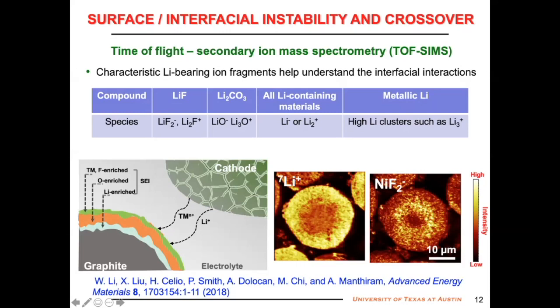We have also used time of flight secondary ion mass spectrometry. That has the unique advantage of producing characteristic lithium bearing ion fragments depending upon which compound you have. So that can help us to have a better understanding of the interfacial reaction between the electrolyte and cathode. One important aspect is, if you have metallic lithium on graphite, you will get a lot of Li3 clusters compared to other compounds. So that's a way we can detect whether metallic lithium is deposited on graphite or other components. In addition, you can sputter, and we can see as you keep sputtering how the components are changing, and you can also use isotope enriched cathode, and you can understand the cathode electrolyte interaction.